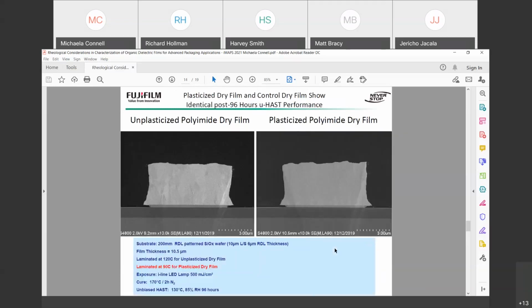So next we have reliability studies. Here we performed a 96-hour unbiased HAST at 130 degrees Celsius with 85% relative humidity. The films were laminated on an RDL patterned silicon oxide wafer with 10 micron line space and 6 micron copper structures. This was laminated with approximately 10.5 micron dry film.